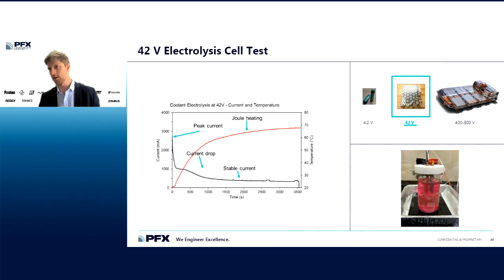And then what we can measure is a number of critical parameters, right? So we'll look at our peak current, how much current passes between the electrodes, and the temperature, as I mentioned earlier. Anytime you have current passing through a conductive medium, you're going to have joule heating or resistive heating. That's this red line. And then we look at the profile of the current over time. So current depletion, do we have passivation? Does it increase? There's a lot of different trends for different fluids. This is just one specific example.